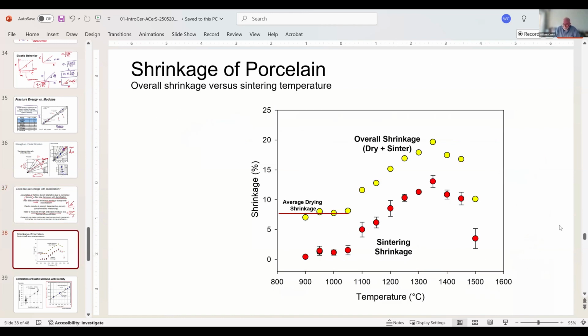I show you this data for porcelains. We've generated a huge amount of data for porcelains and for aluminas and zirconias and what have you. But the red dots here are the sintering shrinkage. This value is where we started in the system. It's corrected for that. So these are my dry pieces, but they started off at a smaller end, and this is my overall shrinkage. So this level here is my sintering shrinkage. And then I come up and I go through a peak. It's actually parabolic. You can describe it pretty well with a parabola. And I get a peak up here.